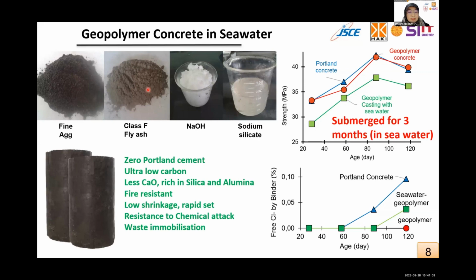In our previous study, we found that in the seawater, geopolymer concrete strength is comparably similar to conventional concrete. And surprisingly, for casting geopolymer in marine area, we can just use seawater as the alkali liquid to replace clean water. So we don't need to use clean water or high quality water or river water and drinking water. For example, we just use the seawater to replace the liquid.